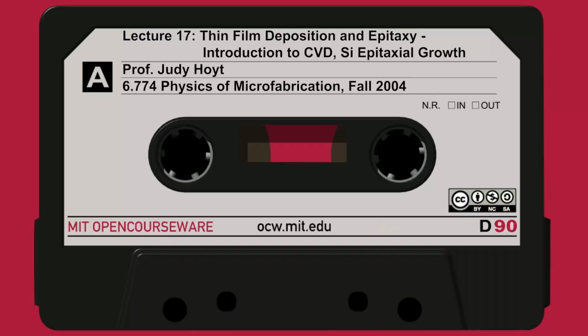And then we have to transport the byproducts through the boundary layer. And then finally, transport of that out of the reactor, out of the deposition zone. I've highlighted here in red steps 2 through 5 because they're most important in determining the growth rate. In fact, the two rate limiting steps tend to be step 2, which is transport of the reactants through the boundary layer, which is typically a diffusion type of process, and a reaction process. The second rate limiting step is the surface processes themselves, the chemical reactions usually.